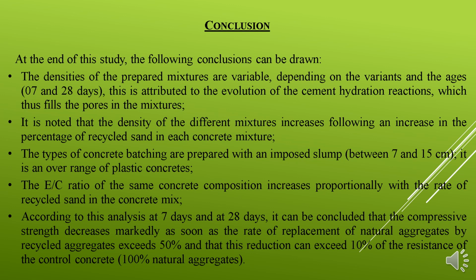According to this analysis, at 7 days and at 28 days, it can be concluded that the compressive strength decreases markedly as soon as the rate of replacement of natural aggregates by recycled aggregates exceeds 50%, and that this reduction can exceed 10% of the resistance of the control concrete.